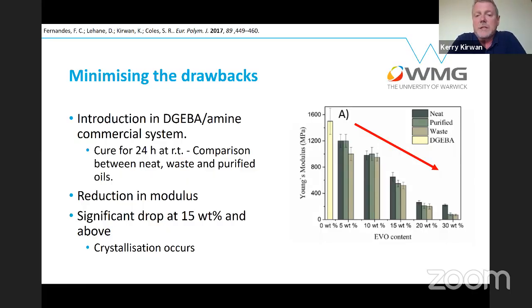So we started along this path. The industry standard is DGEBA. Now, DGEBA-based epoxies are trying to be phased out. They contain bisphenol A and other unwanted chemicals. And so what we were looking at is, like we did with diesels, could we start introducing a bio or a waste bio content into a commercial blend? And what you see here is we looked at different types: 5%, 10% of fresh vegetable oil, used vegetable oil, and then used but treated vegetable oil.